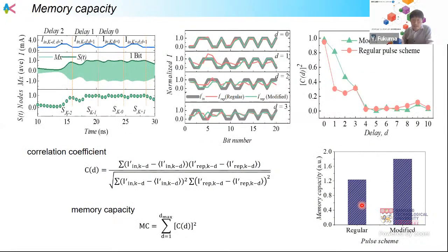To understand this behavior, we checked the memory capacity of this spin Hall oscillator. The memory capacity is a property of the network to linearly reconstruct the past input signal using the present input. What we did here is input a random pulse sequence like this, then try to reproduce it by using delay 0, delay 1, delay 2, or delay 3. What we can see here is the modified scheme with the excitation part, and the regular scheme is the first scheme.